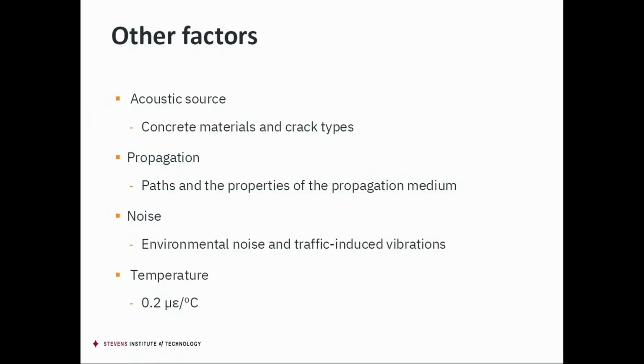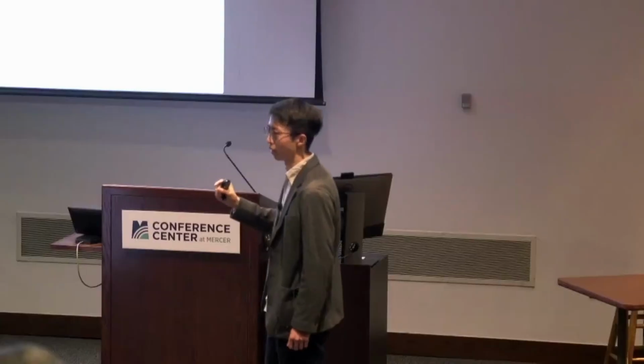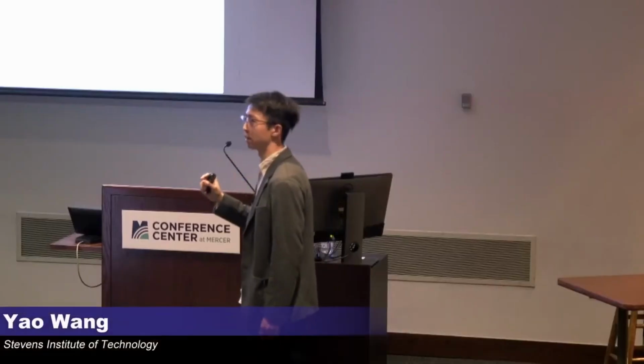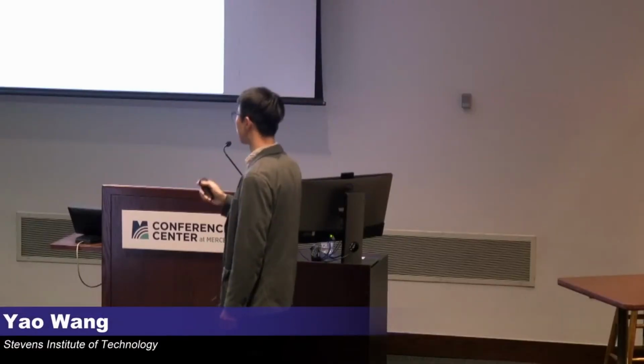We can use temperature compensation, such as installing another distributed temperature sensor. And the temperature change is always a long-term change, at least minutes or hours, but the cracking signal is at the millisecond level. So it's easy to do the compensation.